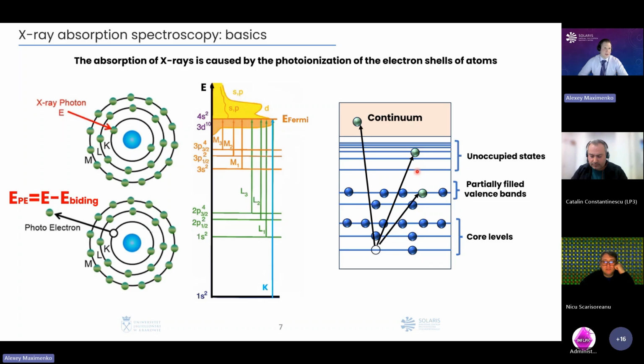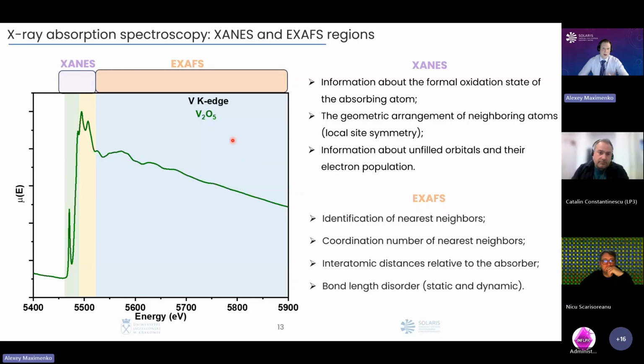And in the case, for example, of 3d metals, such as vanadium or chromium, the transition from the 1s level to the 3d level is not allowed. But when you have a distortion in your material, you have a hybridization between 3d and 4p levels. In this case, the transition starts to be more probable. And the more this hybridization appears, the more probable the transition is. For example, if we speak here about vanadium K-edge, this is actually a transition to the 3d-4p hybridized orbital